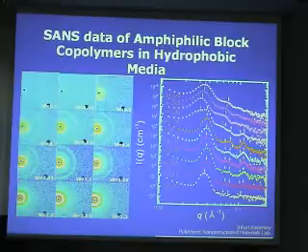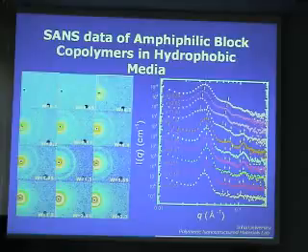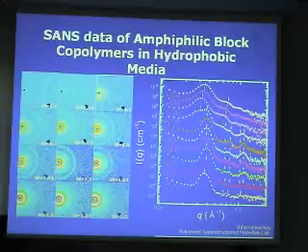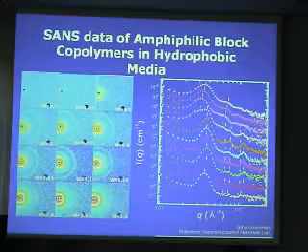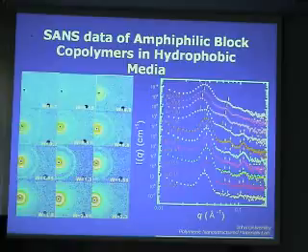When you look at this data, when you increase the water content in the solution up to W equal to 1.3, we have almost the same peak profile. Then at W equal to 1.55, we have some change in the peak profile. We have some peak in the left shoulder of this major peak, and some other peak comes up.